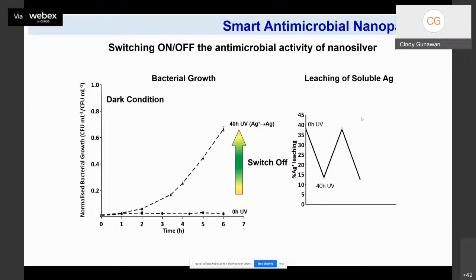But now, can we actually switch on and off the antimicrobial activity of nanosilver? So this is the one that we have before, the as-prepared nanoparticles without any UV illumination, and this is the growth profile when the nanoparticles have been exposed to UV illumination, which means that the silver ion deposit has been reduced to metallic silver, and therefore the switching off of the antimicrobial activity. And this is the corresponding extent of leaching of the nanoparticles. At 0-hour UV, you have a high extent of Ag leaching, and then with 40 hours of UV illumination, we have a low extent of silver leaching.